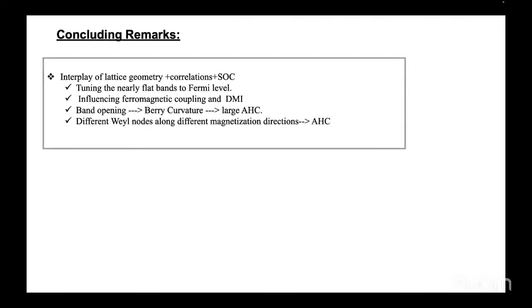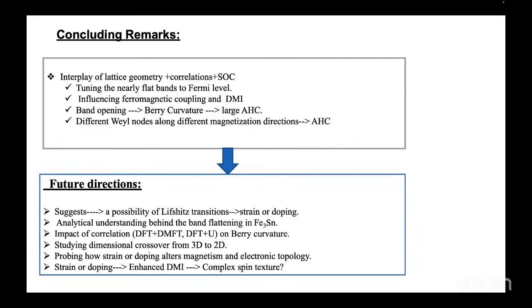So this brings us to the concluding remarks of my studies: we see a great interplay of the lattice geometry, correlation, and SOC in tuning the near flat bands towards the Fermi surface, influencing my ferromagnetic coupling and DMI, and in turn also influencing the band opening and the Berry curvature, resulting in maybe changing the anomalous Hall conductivity and the presence of Weyl nodes along the different magnetization directions we observed. As a possible future direction, we suggest that there can be a possibility of a Lifshitz transition if we include strain or doping in the system.